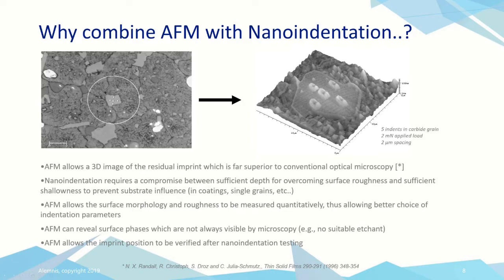If we zoom in on this with AFM, you can see the image on the right, we start to see the pileup around these indents is actually very significant. And this is not something that we could see just from the load depth curve. So AFM imaging is crucial to understanding what's happening.